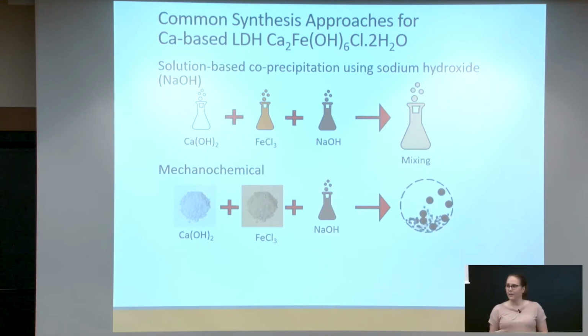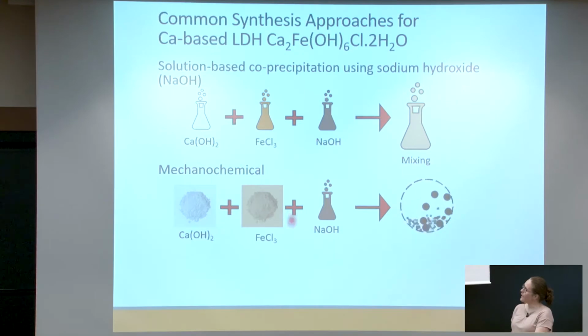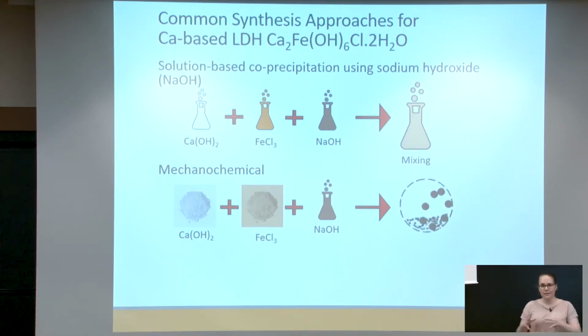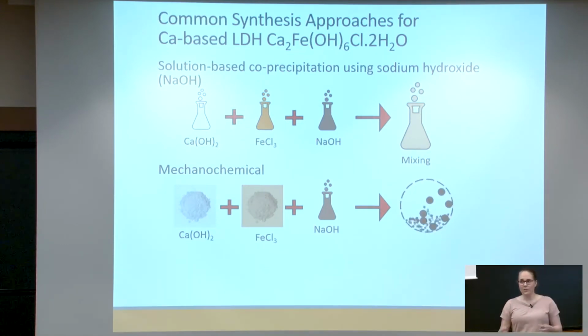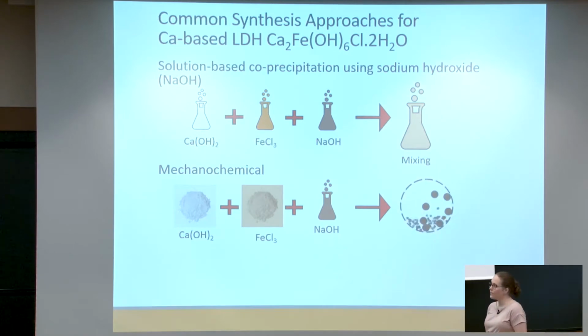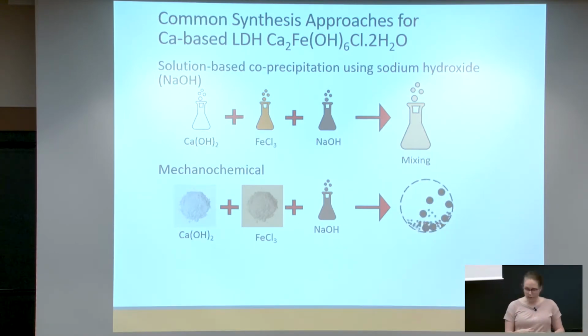The other one is a mechanochemical approach, whereby you take the powders, not liquids, and here it's assisted by a liquid, this sodium hydroxide, and then you put it into a mill, a ball mill, whereby the energy from the mill and the balls moving around at really high kinetic energy means that the powders are being essentially squished together, and the high energy can cause changes in the structure of the material. And so what happens is you transform from having these starting materials into the layered double hydroxide.